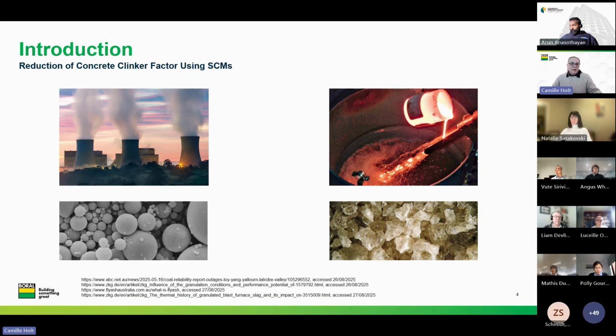The use of SCMs imparts favourable properties to concrete, aside from lowering the embodied carbon, such as increases in durability. And these, again, are all well known and understood in our industry. But what we also know, as Arun said, was that over time, our two favourite SCMs, slag and fly ash, will increasingly become more difficult to source. With less carbon-intensive steel manufacturing practices and the shift towards renewable energy, this will mean a reduction in the availability of blast furnace slag and fly ash in the future. So there is a need to find another SCM source to bridge the gap and allow us to sustainably continue providing our customers with lower carbon concrete.